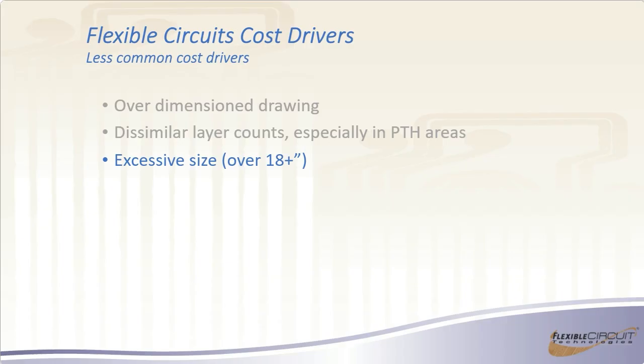The other limiting factor is your lamination presses. Most of those don't go over about 3 feet in any dimension. So we typically have to put seams in the cover. But if you don't have any plated through holes, we can probably go 8 or 9 feet. But like I said, there will be a cost associated with that, and there's a number of caveats that we would have. Another thing would be plating. We wouldn't be able to have plated through holes. It'd have to be limited to a single-sided circuit. So there's a lot of what-ifs that you have to go through to determine what the actual maximum length is that you can do.